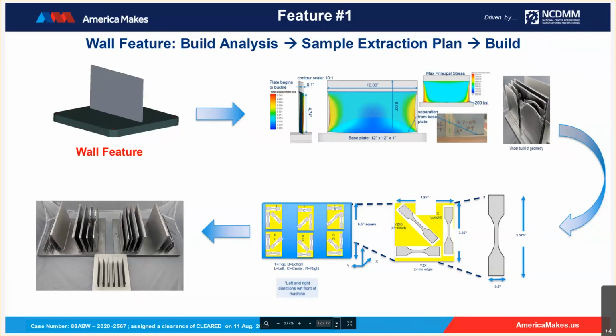And once we were able to build the walls, you can see in the bottom left, a bunch of the walls with different thicknesses were built with different build strategies and build parameters being employed. We could actually define a way to extract these samples out. Once we have the walls built, you can use the zone-based criteria to look at the top left, top center, top right, or bottom left, bottom center, or bottom right zones. And while we test the samples, the flat tensiles were taken out, taking into account the orientation of the samples with respect to the build direction. So you have the wall build parameters, the wall build strategy, the location from where you are going to extract these samples, and the orientation of the samples with respect to the build axis, all taken into account when we walk the line from processing, structure to property.